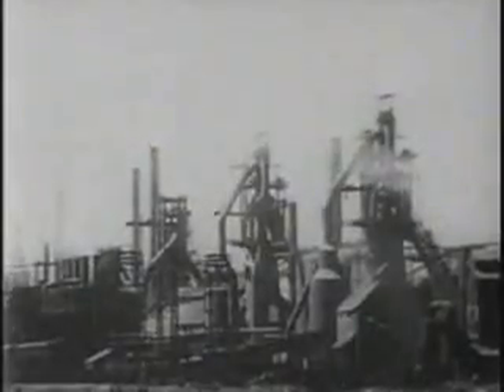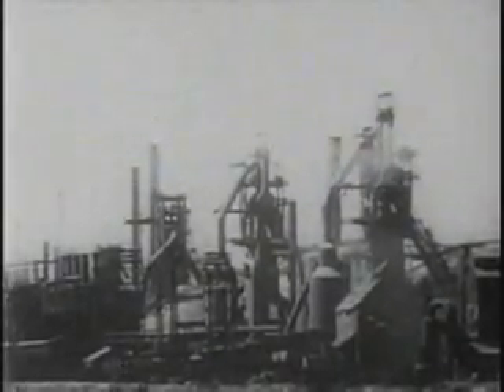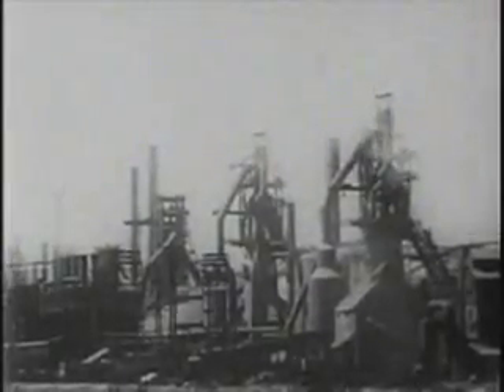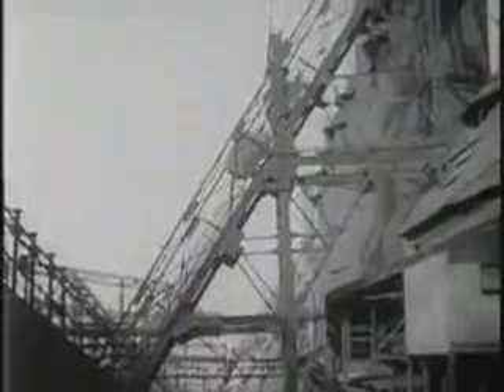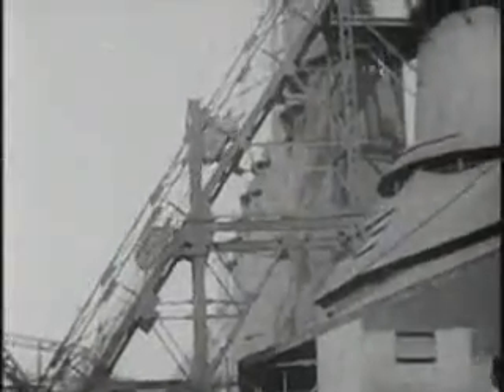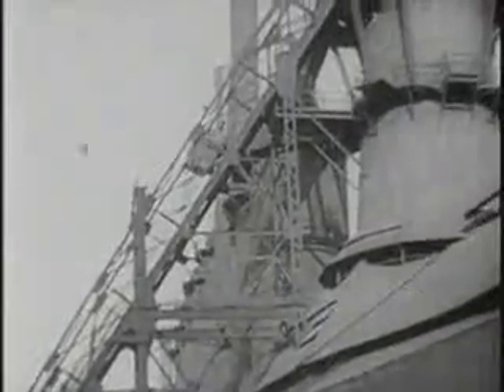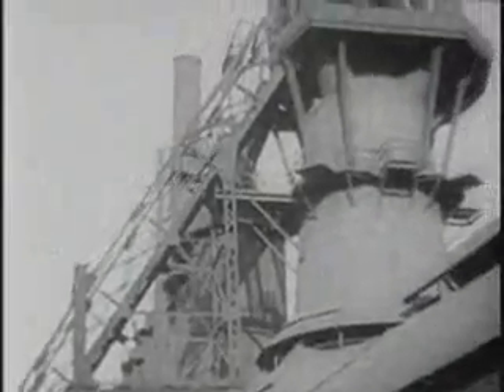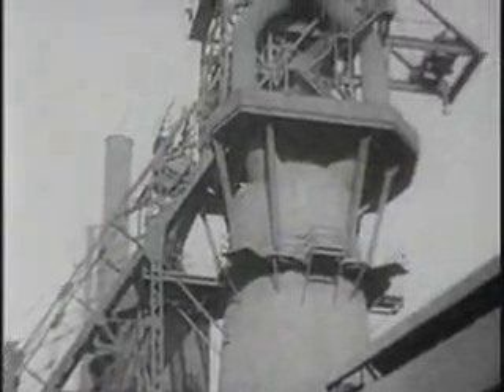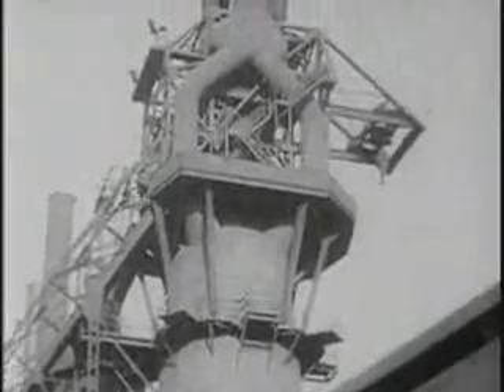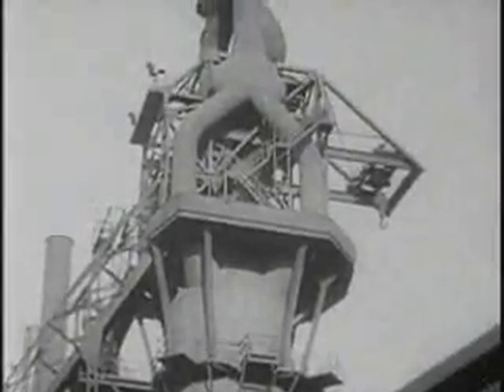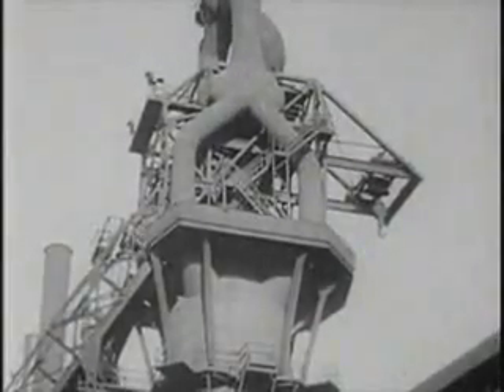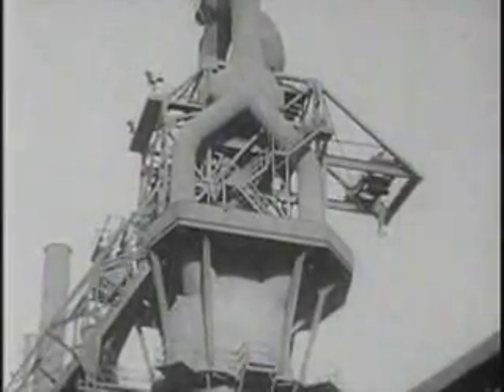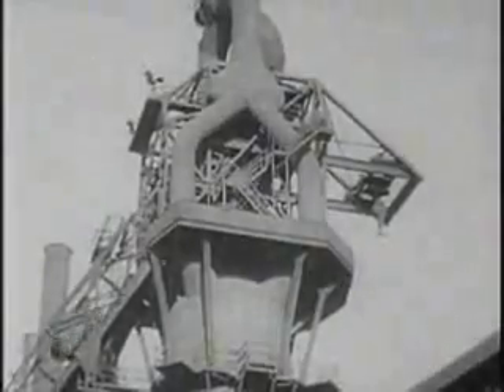The first step in making steel takes place in the blast furnace. Here the oxygen and impurities are removed from the ore and the iron reduced to a liquid. Up to the top of the blast furnace go skips with accurately weighed loads of iron ore, coke, limestone, up and down continuously, for one of these giants eats up 3,500 tons of raw materials a day. Making 1 ton of iron requires approximately 2 tons of iron ore, 1 ton of coke, half a ton of limestone, and 4 tons of air.